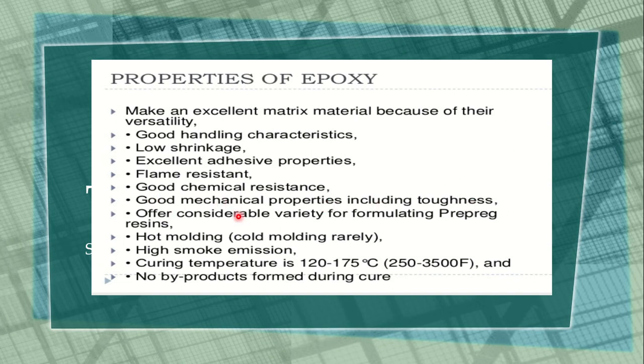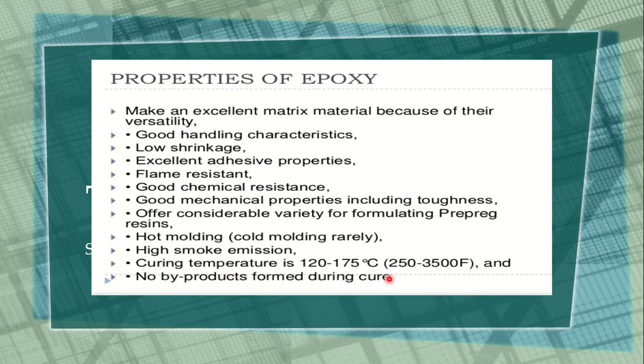Properties of epoxides include: excellent adhesive properties, flame resistance, good chemical resistance, good mechanical properties including toughness. They offer considerable variety for formulating prepreg resins, hot moldings, and cold moldings (rarely). High smoke emission. Curing temperature is 120 to 175 degrees Centigrade (250 to 350 degrees Fahrenheit). No byproducts are formed during cure — this is a very important property of epoxides.